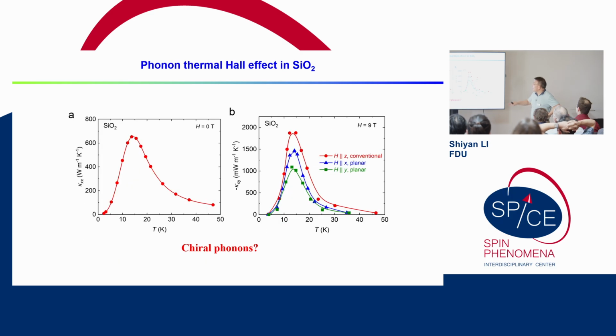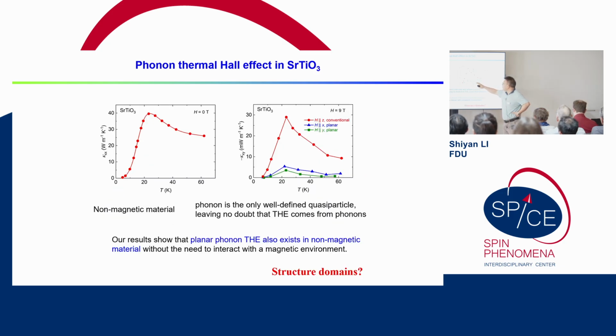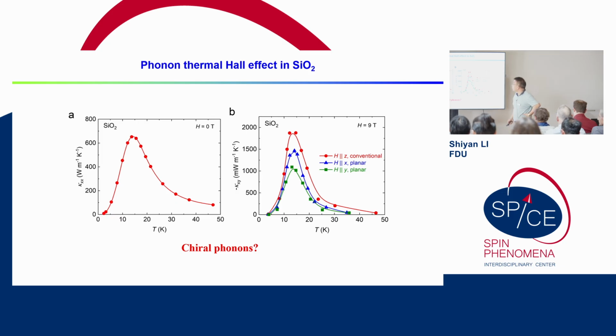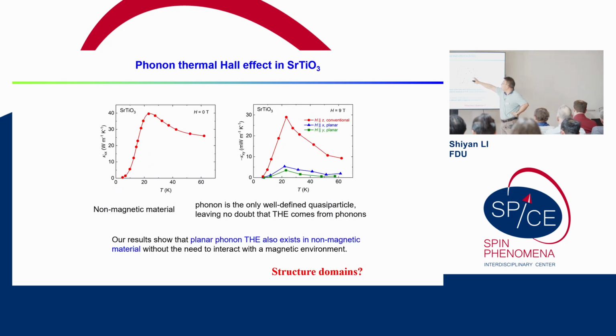Okay, so for this single crystal, we just bought it, and this is the thermal conductivity. This is thermal Hall in all three field directions. This value is also giant. So that's great, chiral phonons, it has this very large thermal Hall. And it also has a planar thermal Hall. Because quartz has this planar thermal Hall, we also measured the planar thermal Hall of STO. We also observe this signal. It's smaller than the conventional one, but it's there. So that's great.